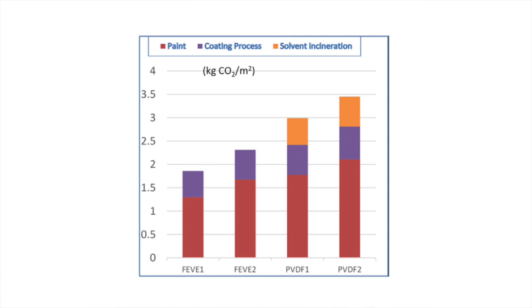The results of this carbon footprint analysis are shown, and you can see that when you look at the FEVE systems, again, these are those powder coating systems, compared to the PVDF systems, you see a big difference between the actual carbon dioxide output, and of course the calculation presents it as weight of carbon dioxide per area. In this case, it's kilograms of carbon dioxide per meter squared. So again, this is the output or the impact, the carbon footprint of utilizing these coating systems to, say, coat extrusions for a curtain wall. And so you can see in this chart here that with the FEVE powder systems, in both cases, one at the 70% transfer efficiency and then one at the 90% transfer efficiency, you have a significantly reduced carbon footprint than you see with the PVDF solvent system.